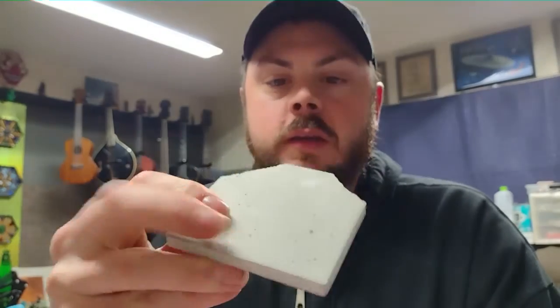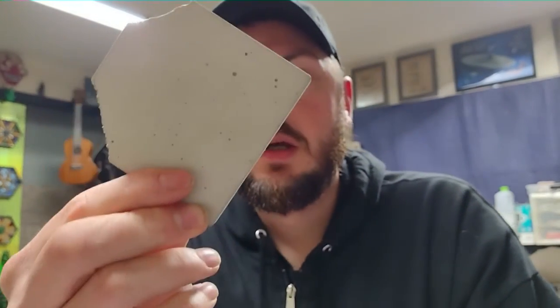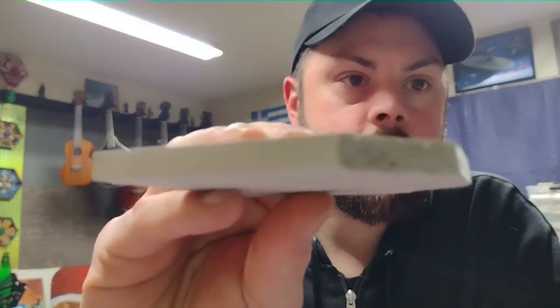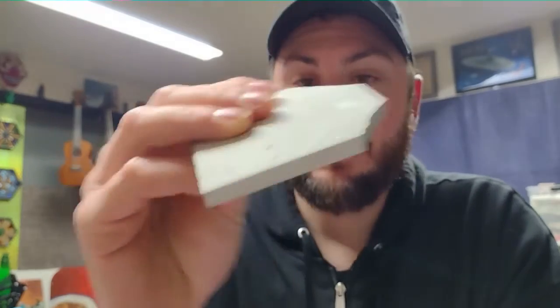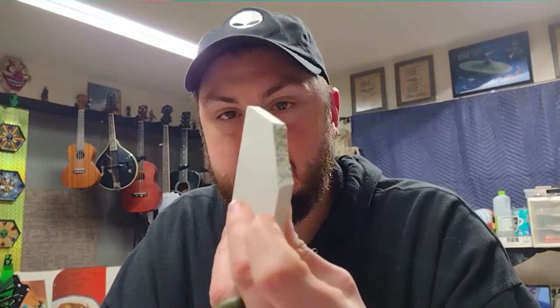Because for one, obviously, it kind of sabotages the structural integrity. Plus, because of how thick it was, as you can see, I got a lot of bubbles there. But also, it really did nothing to the finish. It didn't color it at all. You can kind of see on the broken edges there the green bits of sand, but it's not worth it, really. So I wouldn't bother putting sand in with your Resin-Crete or Pure Cure. It just weakens it too much. So that's garbage.